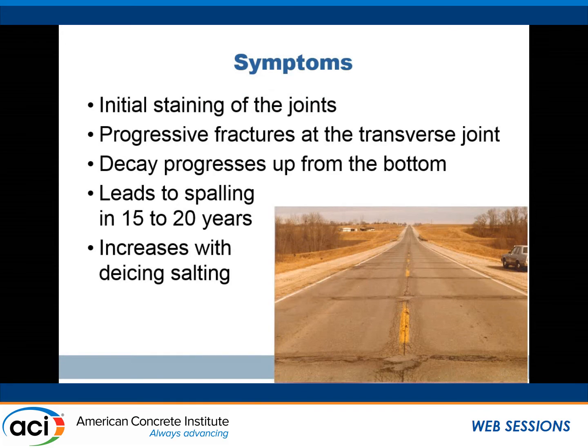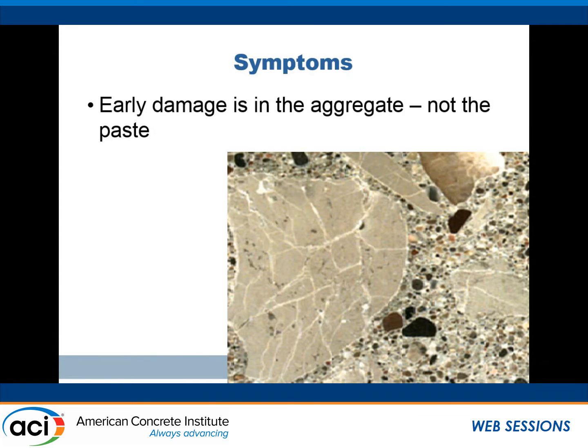So again, we've already heard a lot of information about what it typically looks like, how quickly it starts to fall apart. The same sort of numbers that Tom and Randy have talked about: in 15 to 20 years, it starts off with the staining, and then the cracking develops, and it's not very pretty. This is one that hasn't been talked about. The de-icing salts seem to make it a little bit worse. Again, images that are not very different.